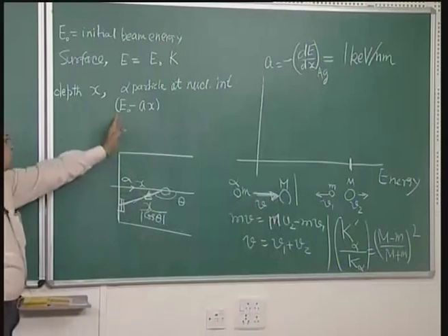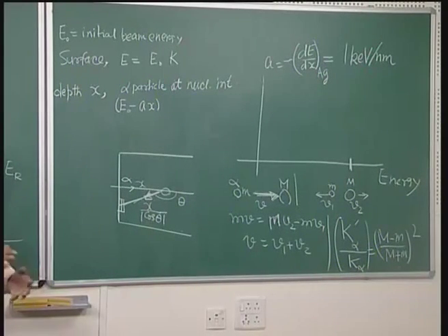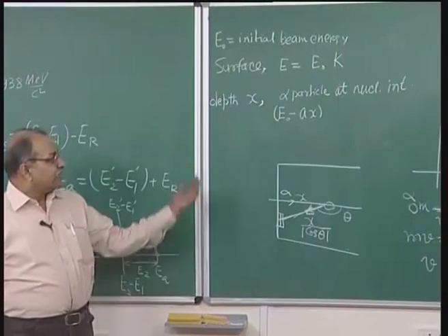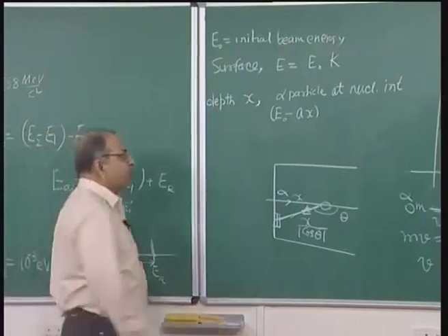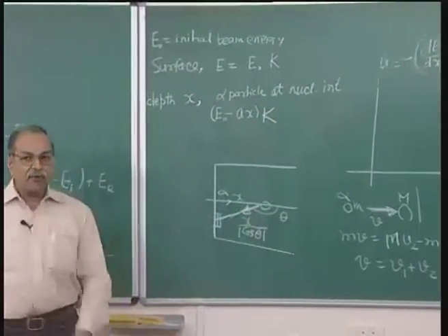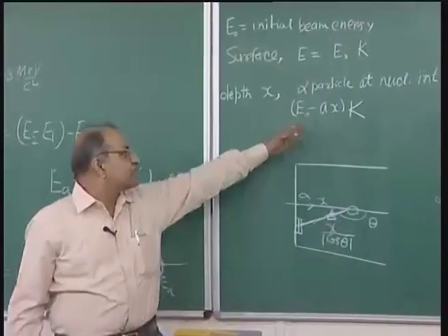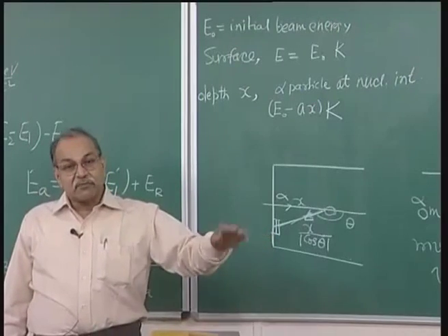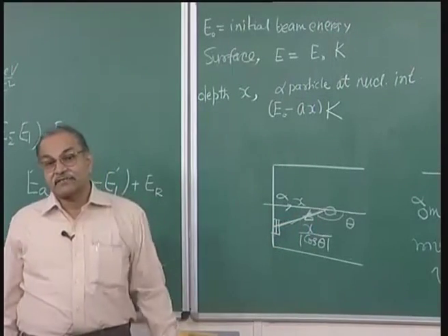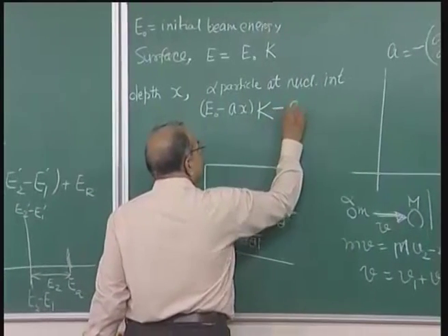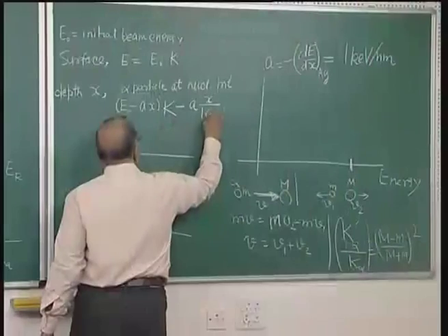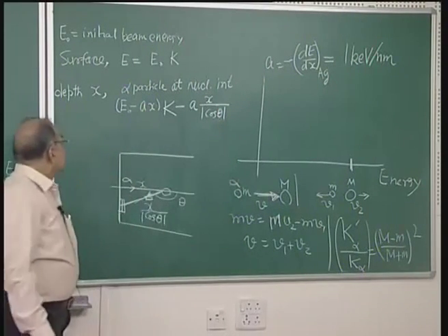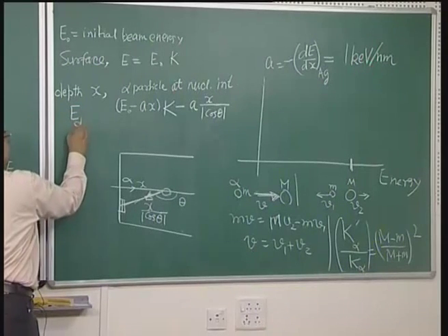So, this is the energy with which this alpha particle collides with that nucleus. Then it is multiplied by that kinematical factor k. When the alpha particle backscatters, it has this much energy, and then it comes through that solid, comes out of the solid and reaches the detector. During that process, it has lost this much energy. So, this is the energy which is detected.